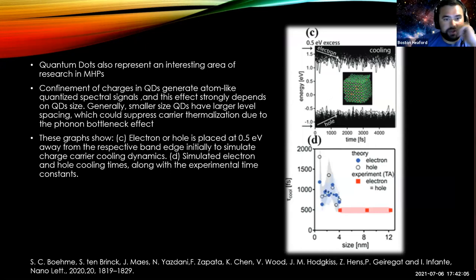And so one of the last things that was mentioned in the study are quantum dots, which are another interesting area of research in metal halide perovskites. Confinement of the charges in the quantum dots generates atom-like quantized spectral signals. This effect will strongly depend on the quantum dot size, and generally smaller quantum dots have larger level spacing, which can suppress carrier thermalization.